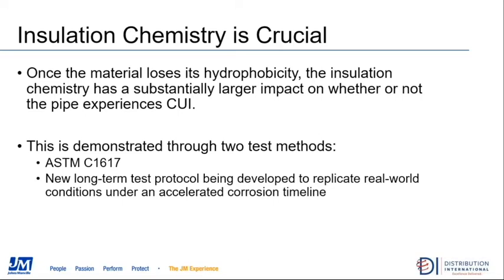And what they are looking to do is try and develop a test method, test procedure that is more indicative of real-world conditions, but does it in a highly accelerated time frame such that they can look at the impact of corrosion in about a 6-month test cycle to be equivalent to what the material might see in a 15 to 20-year exposure in the real-world conditions.